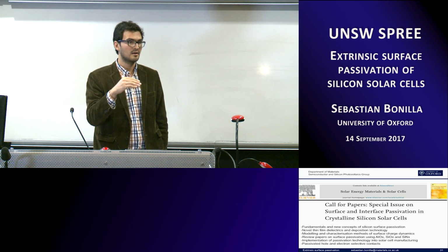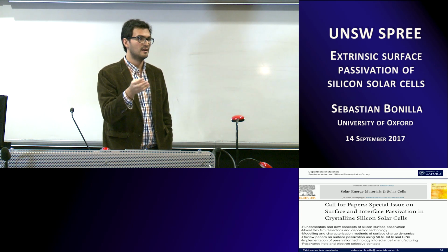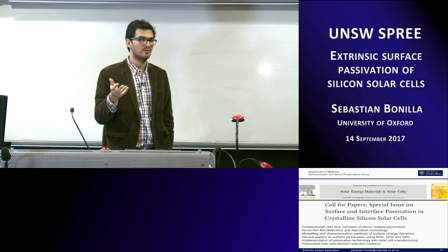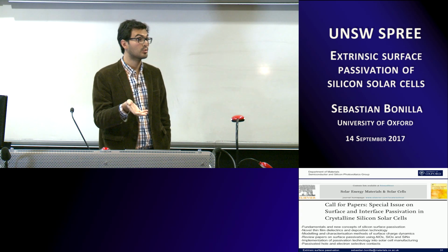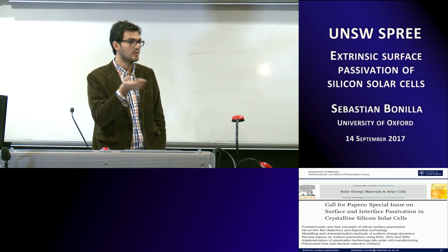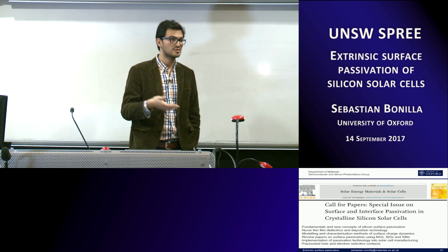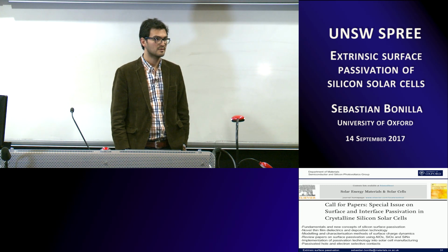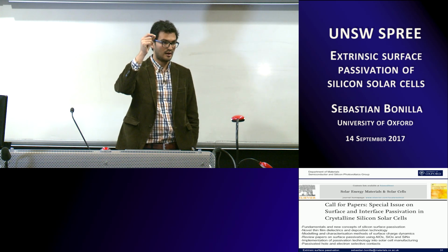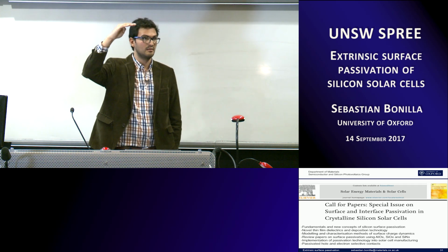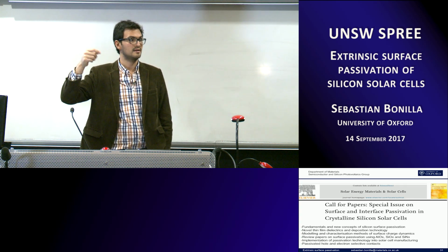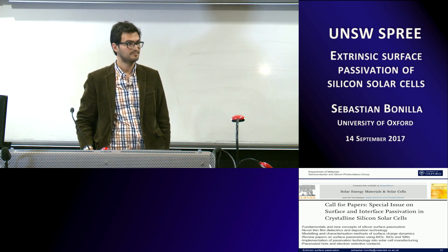So in that sense, we were not very worried about PID damaging the passivation provided by ions. But the expectation is, of course, if you had a very strong electric field, once you elevate the temperature probably above 100, 150, a strong electric field will probably pull the ions out. But we believe that's not a problem, because most solutions, a few patented and already public patents, show that the key part of not having PID involves having a direct contact between the outermost part of your dielectric stack and the silicon, such that there is not a high electric field between the two.